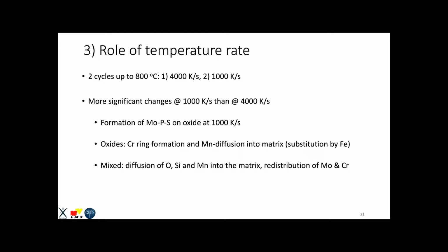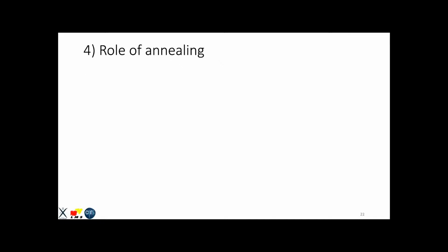We saw that there was formation of non-oxide precipitates on oxides at 1000 Kelvin per second. Again, much more than at 4000. In the case of oxides, there was chromium ring formation and Mn diffusion into the matrix. So this is a common thing that happened every time. And in the mixed cases, we had diffusion of oxygen, silicon, and manganese into the matrix, and redistribution of molybdenum and chromium. Okay. Next, we studied the role of annealing.